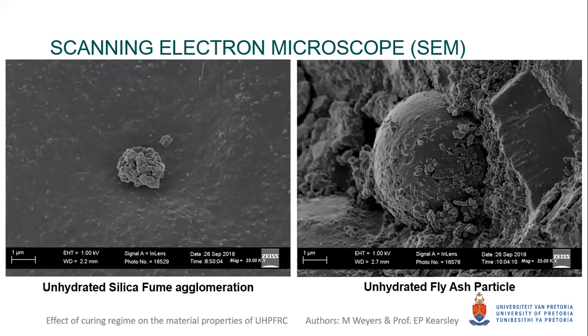These images show an unhydrated silica fume agglomeration on the left and an unhydrated fly ash particle on the right. Both these samples were taken from the inside of an ultra-high-performance concrete cube after 90 days of water curing. Unhydrated particles were observed in samples from both curing regimes. The scale on both images was 1 micrometer.